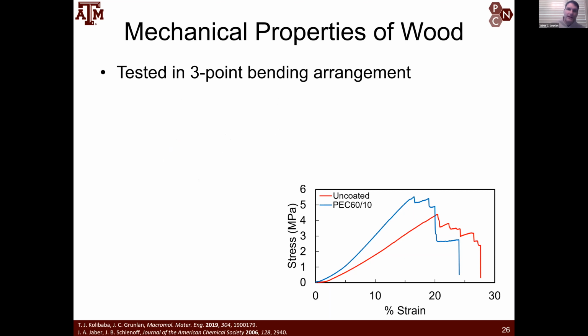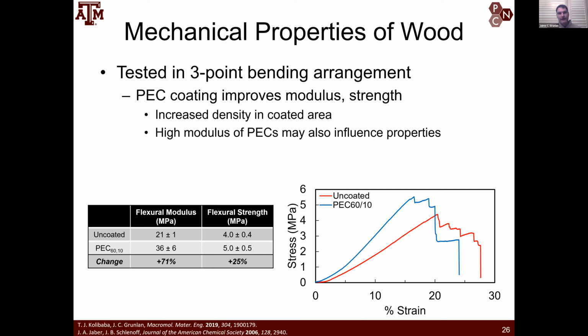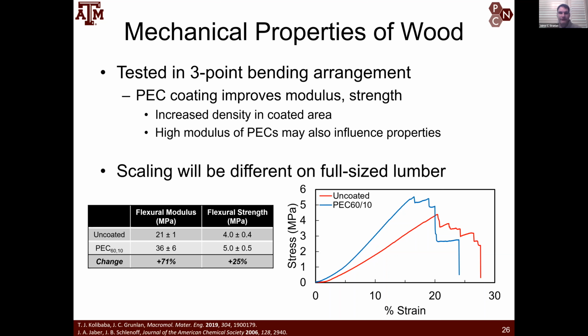To my surprise, it turned out that the wood became stronger as well. So if we look at the flexural modulus and flexural strength of the wood after that 6% coating, you can see that you had a 25% increase in strength and a 71% increase in modulus. So that's quite interesting. It's probably mostly because you had some densification of the wood upon coating. But as I showed in the microscope images, it was still conformally coated and the wood still had its porous structure, but certainly the coating adds a little bit of density, and I imagine that contributes to the improved strength that we're seeing. So it's a nice, unintended beneficial side effect.